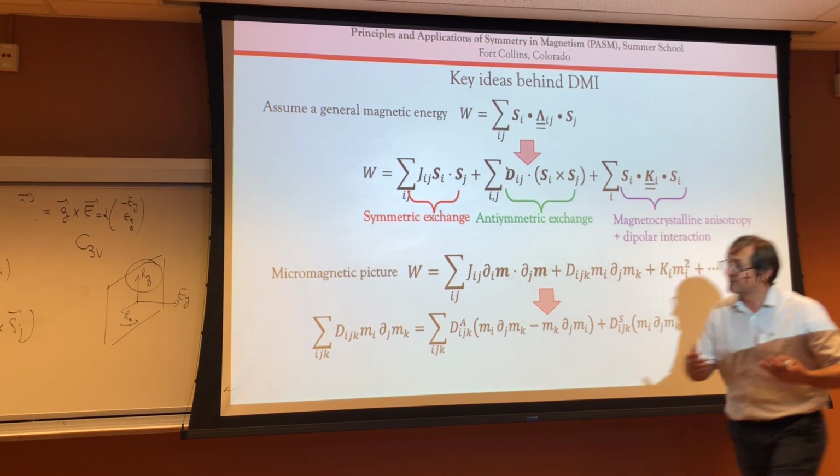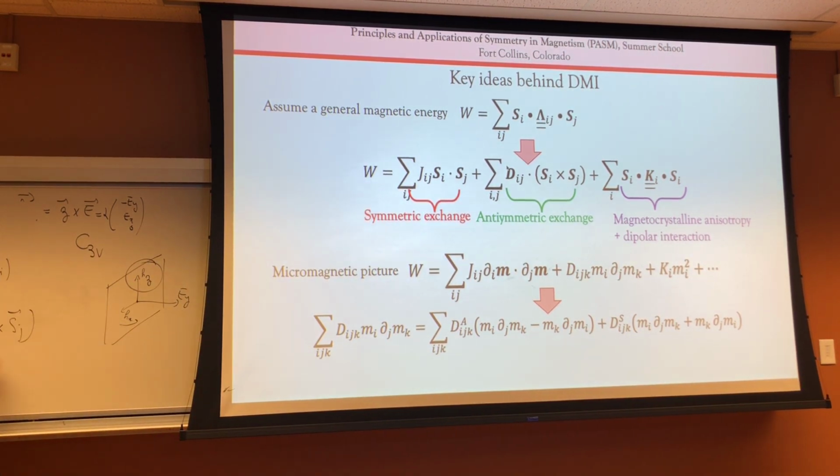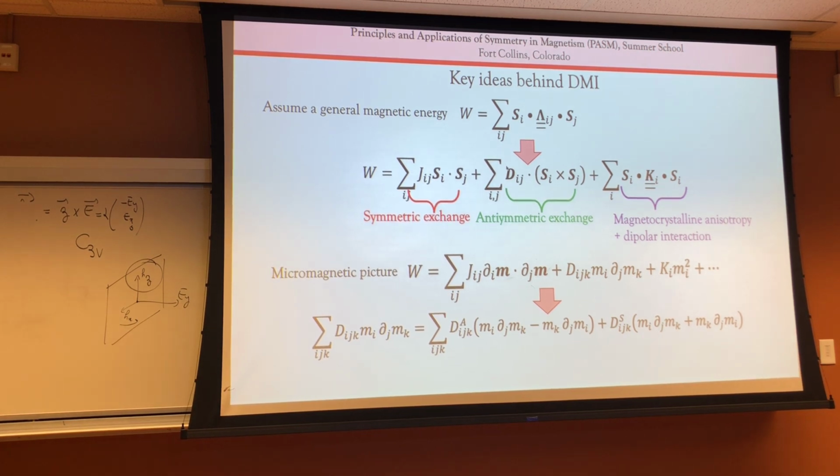So if you take a material with this term here that is linear in the gradient, the anti-symmetric part of your linear term, the one that is proportional to this Lifshitz invariant, will give you chirality. So it can stabilize a chiral spin spiral, it can stabilize skyrmions, these kinds of things, even merons, so some interesting systems.